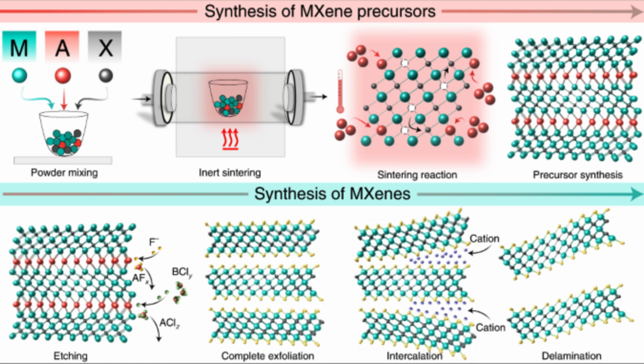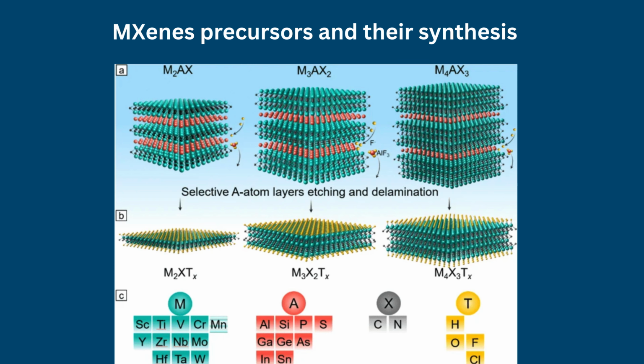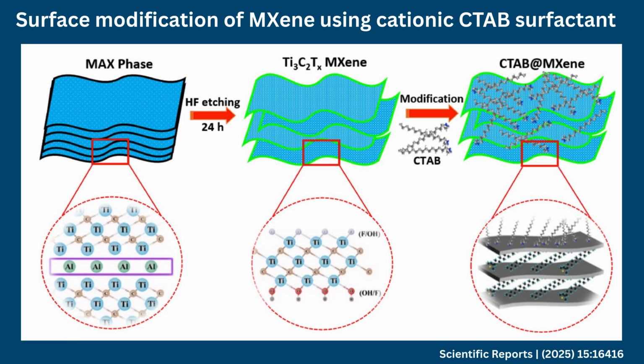MXenes possess a layered hexagonal structure, in which transition metal carbide or nitride layers are stacked through van der Waals interactions. Surface terminations such as hydroxyl, oxygen, and fluorine strongly influence their electronic structure, conductivity, hydrophilicity, and chemical stability. The interlayer spacing can also be tuned through ion or molecule intercalation. For example, cationic surfactants have been reported to increase the interlayer spacing of Ti3C2Tx by more than 170%, thereby enhancing ion transport and electrochemical performance.